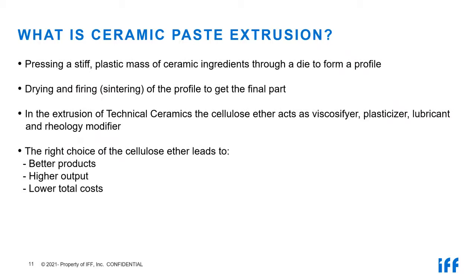After the extrusion step, normally a drying step of the profile is required, followed by firing and sintering of the profile to get the final part. Maybe a little bit of post-processing is still required. This depends. And of course, in such a typical recipe, a cellulose ether is always a big contributor for the processing, but also for the final properties. This is not always so well known, but I will give you some more insight. Cellulose ether acts as a viscosifier, as a plasticizer, as lubricant, and as a rheology modifier.